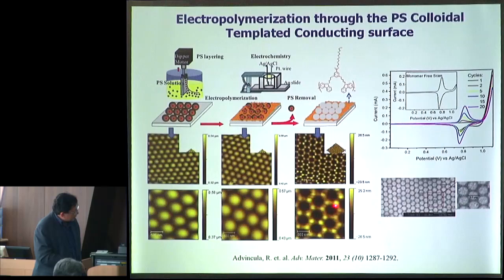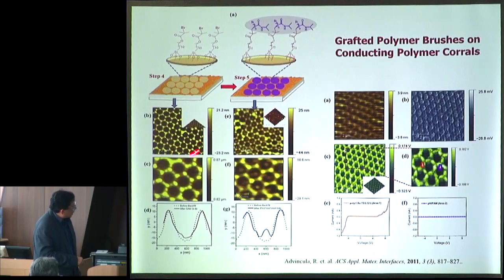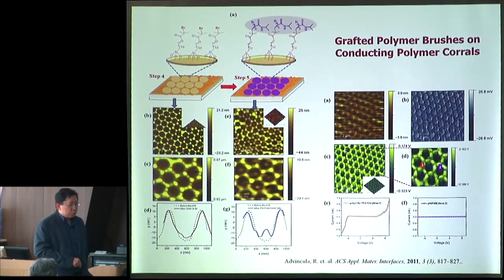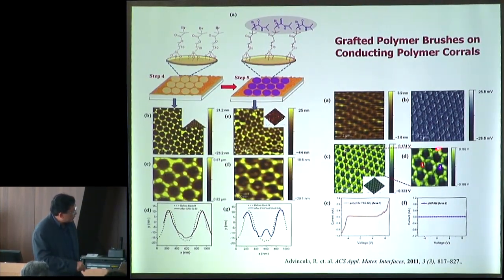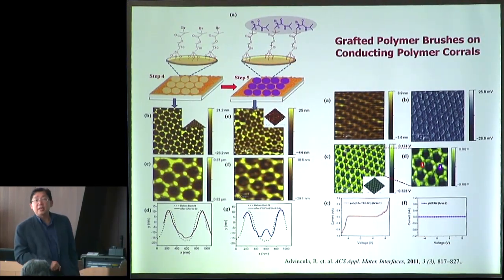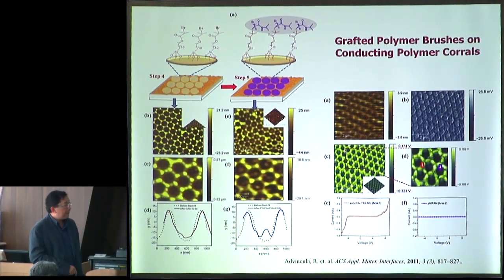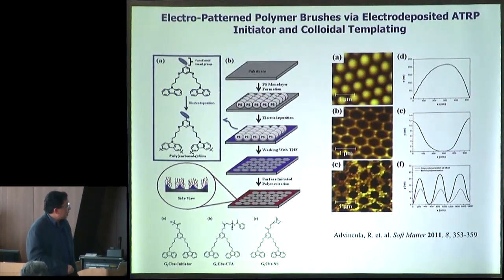But then the middle part here is still electrode, ITO or gold, okay? So that middle part, we can then graft an ATRP initiator and then grow a polymer brush. So this is basically a conducting polymer with polymer brushes in the middle. To do another analysis, we use conducting AFM to show that the green versus the blue region represents a more conducting IV junction versus an insulating or non-conducting junction. Okay? And this colloidal templating can in fact be extended to the previous work.